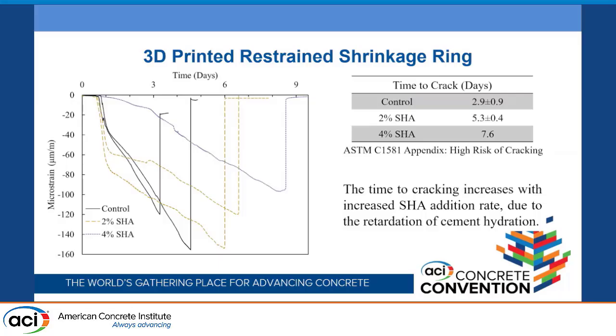First and foremost, with our shrinkage ring data, we looked at our time to crack, a relatively good measure in the ASTM for your risk of cracking. As you'd expect with a 3D printed concrete mix with a high amount of paste, there is a high risk of cracking, but we can also see that the inclusion of a self-healing agent is extending out that time to crack. This is pretty much a function of the inclusion of the self-healing agent, also including some sugar to allow the healing reaction to occur. What we're seeing is an extension, but not a meaningful one in reducing the risk of cracking ultimately.